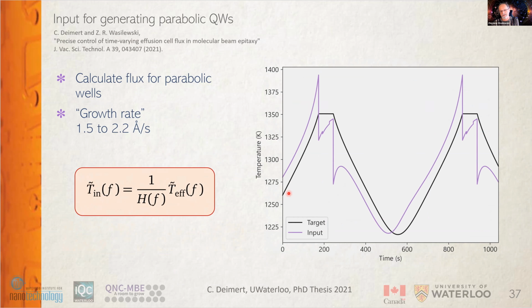this. The black line is the desired trace of temperature to get the parabolic potential. So this is the temperature of the cell, so that's why it doesn't look parabolic, but it will translate into parabolic potential. And the magenta line is what you need to request from the cell to really get the right flux. So this is pretty wild, and you would never come up with that without this technique. And it turned out that with this technique, with a normal growth rate, and we have to grow like 50 plus of those quantum wells, it would take forever if we were to grow really slowly and rely on our normal flux calibrations.